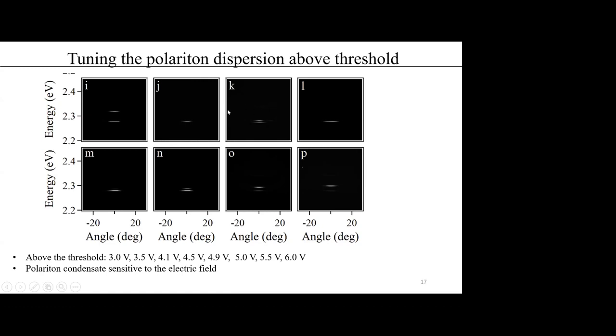They are shifted along the Kx direction, depending on the polarization. In addition, we found that the polariton condensate is very sensitive to the external voltage applied across the microcavity. For example, the LP4 condensate cannot condense when the voltage is larger than 5.5 volts. The reason for this, we believe, is that the voltage on the microcavity modifies the electric field distribution in the cavity layer. So in this case, the external voltage directly allows us to manipulate the population and the threshold of the polariton condensate.